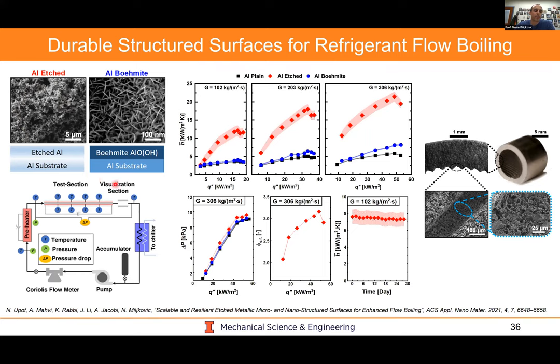And in this case, this is actually refrigerant experiments looking at the heat transfer coefficient as a function of different mass flux. This G here is the mass flux, not the adhesion. And you could see for the surfaces that we've made here, we could actually have an enhancement of about 300%. We also measure pressure drop. We can measure void fraction and then durability over multiple day tests. And then do things like demonstration on real fin tubing, which would actually be used within industry. So not just on plain tubing, but something a lot more relevant. And we're very excited by this work and being able to now focus on super hydrophilic surfaces, which are durable and moving a little bit away from the hydrophobicity.